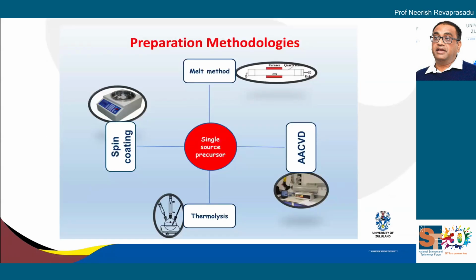So how do we make quantum dots? We use in our lab what is known as the single source precursor method. And so we make metal complexes, and then we heat them at high temperatures with what is known as a thermolysis reaction, and we can form quantum dots in a flask, or we can make them into films, which is AACVD, or we can spin coat them, or what is more popular now for scaling up our materials, we use what is known as the melt method, where you just heat it in a furnace and you basically break down your complex to give you your nanomaterial.